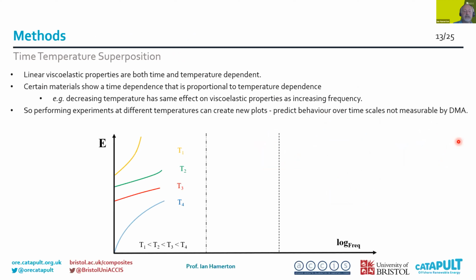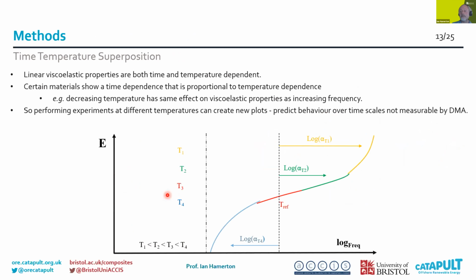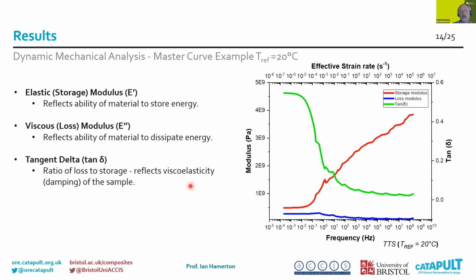So we actually carry out a series of analyses at different temperatures. These give rise to different behavior to monitor how the modulus changes. And then we can simply construct a master curve from all of these data sets. That in time gives us a master curve, and you can see that carried out for 20-degree analysis here for different moduli, the storage modulus, the loss modulus, and the tan delta.